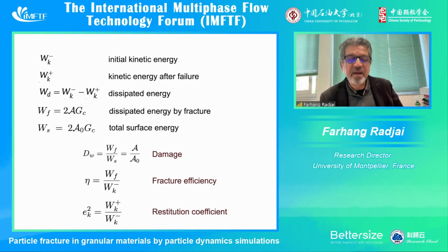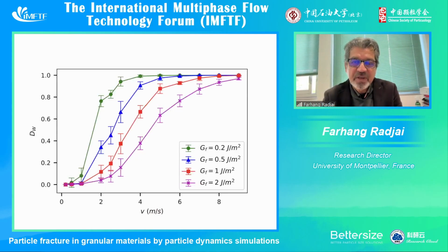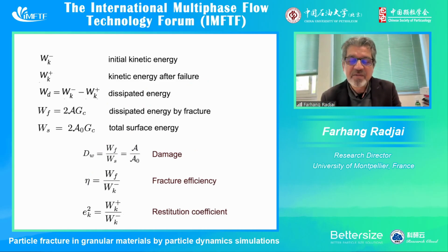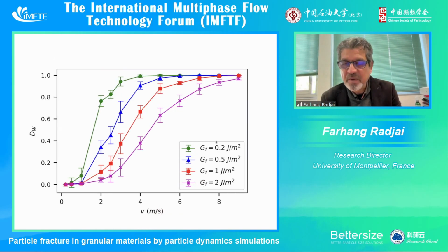And here you see, for example, damage, Dw, which was defined as the amount of surface generated, for different values of fracture energy. As you can see, don't look much at the values of the fracture energy, because we have to look at this in a non-dimensional way. It is mainly a parameter for us, which we change. But of course, it can be made realistic. It depends on the size of the particles that we consider. And as you can see here, for different values of the fracture energy, we have different dependence of this damage on the impact velocity.